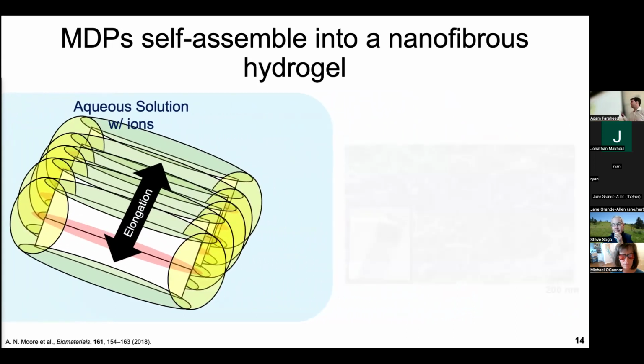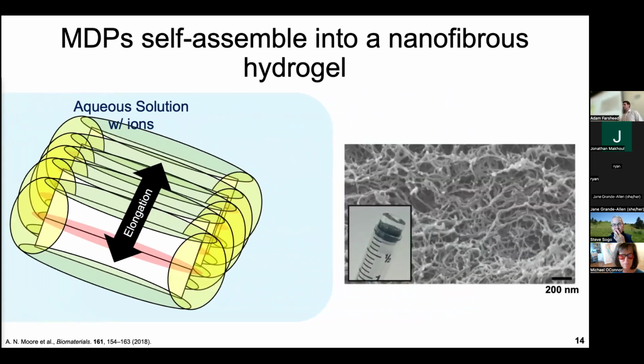And then macroscopically, when we look at this material on the left bottom inset, we can see this little hydrogel puck start to form that's on a syringe. And on the right side, I'm showing you scanning electron microscopy, which is an extremely zoomed in version of our system. And we're able to see nanofibers starting to form. And just to orient you to the size of the picture on the right, a cell would be much larger than this entire image.